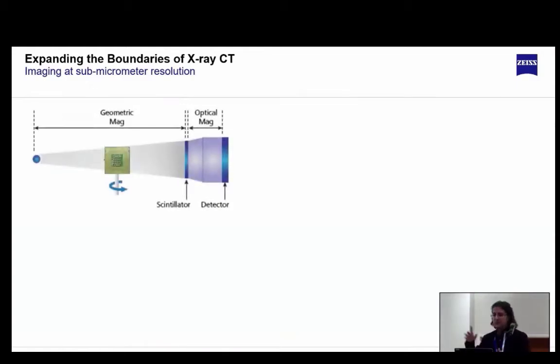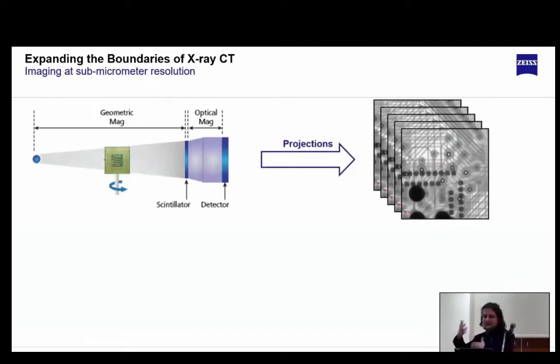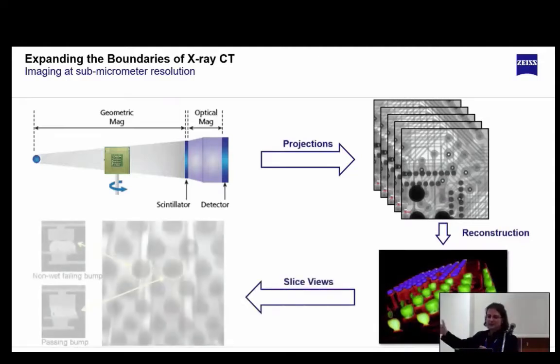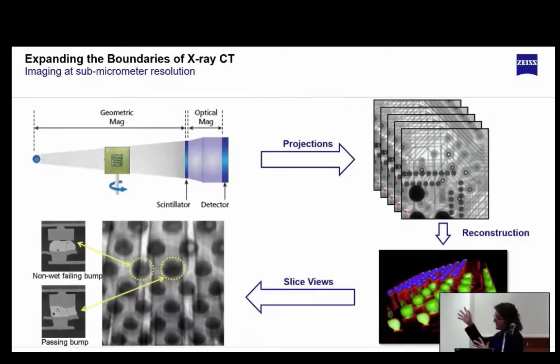In practice, the measurement workflow is composed of 3 basic steps. The first, an operator selects the best settings for scanning the part based on the geometry, size, and composition. And then the X-ray system rotates 360 or 180 degrees and starts collecting snapshots or image projections at different angular orientations. And after collecting several projections at those angular positions, a software reconstruction will generate a 3-dimensional model of the part volume. And this can be used to non-destructively inspect or do quality control of several types of applications from inside of the device.